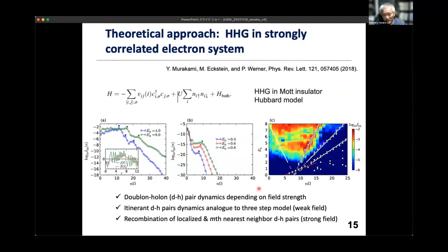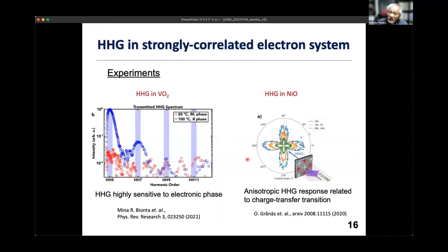And for experiments, very few were reported at the time. In vanadium oxide in the metallic phase, they observed almost nothing, but in the insulator phase they obtained some harmonics like this. And this is nickel oxide, which is also predicted to be a Mott insulator, but they obtained a very anisotropic response.